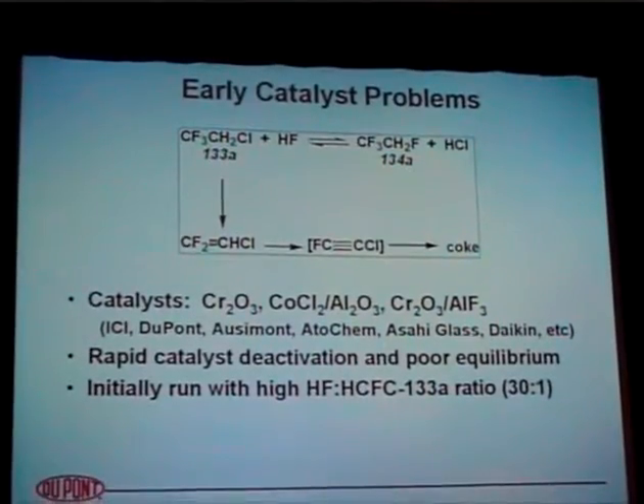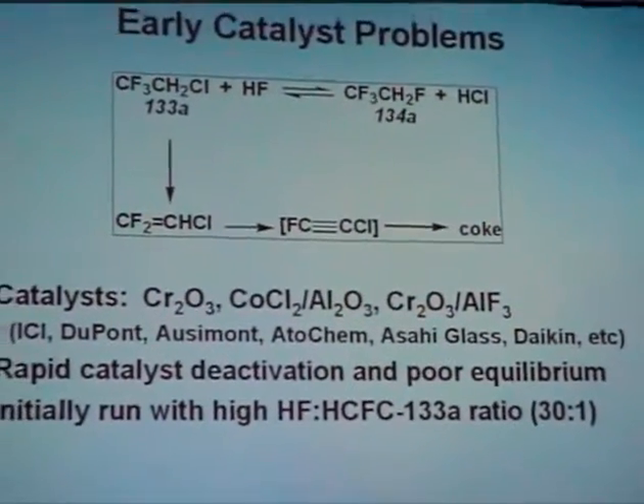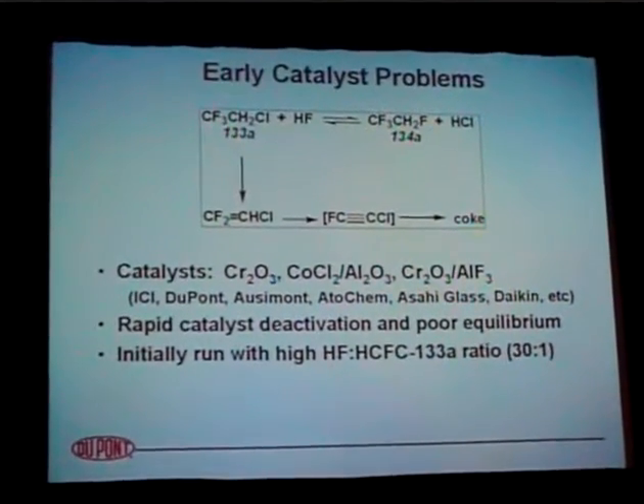When we started looking at that, and other companies started looking at it in the late 70s, actually, for the first time, there were big issues associated with this top reaction. It's an equilibrium limited reaction. Stoichiometric amounts of HF will cause only a 3% conversion of the 133a to the tetrafluoroethane. So to drive that equilibrium reaction requires very large ratios of HF, something like 30 to 1 fed to the reactor. That means a lot of recovery, a lot of recycle, a lot of cooling down, a very expensive process. So the ratio is a big issue. The other problem was that the catalyst died within minutes initially. And that was believed to be due to the fact that HCl and HF are eliminated from that molecule 133a in the upper left-hand corner to give the olefin and then the fluorochloroacetylene. This polymerizes on the catalyst surface and decomposes the catalyst very quickly. So this was the state of the art in the late 80s.